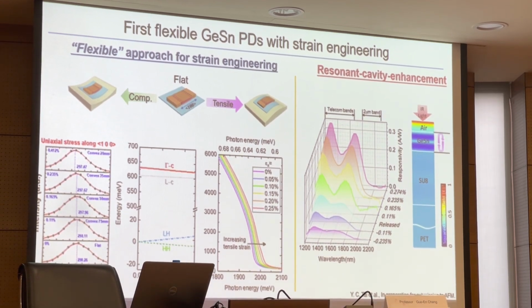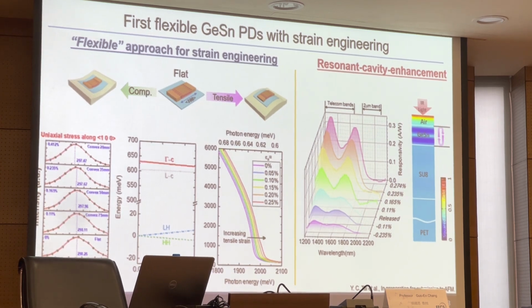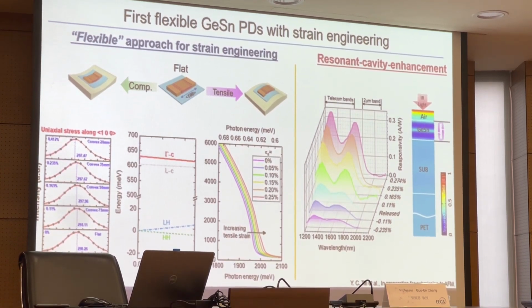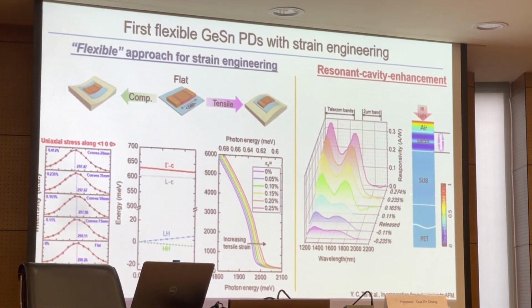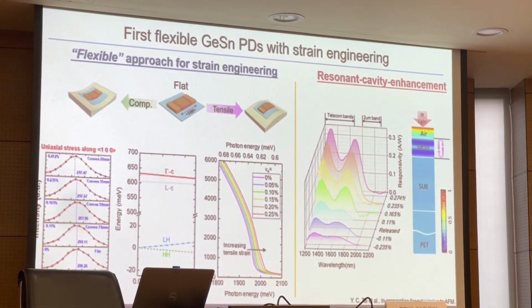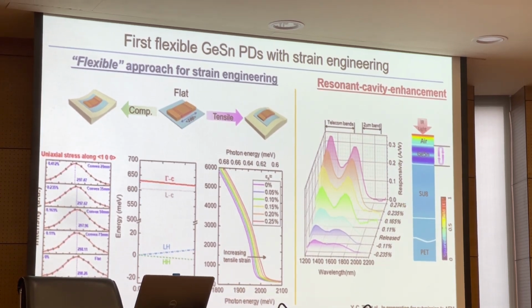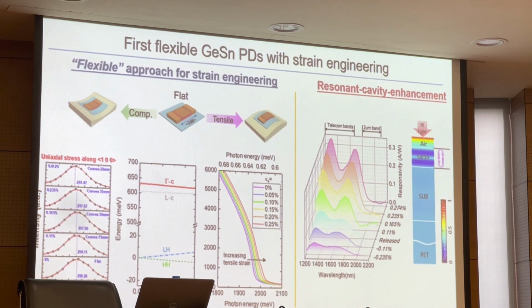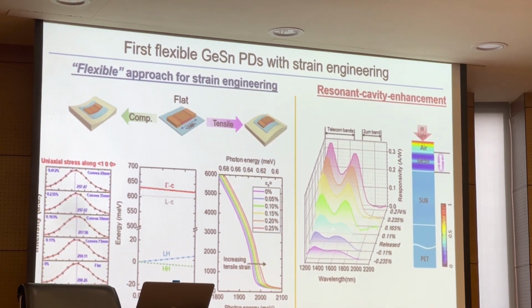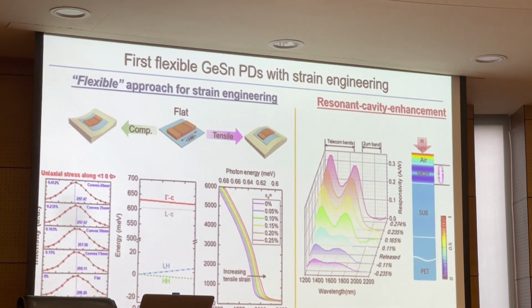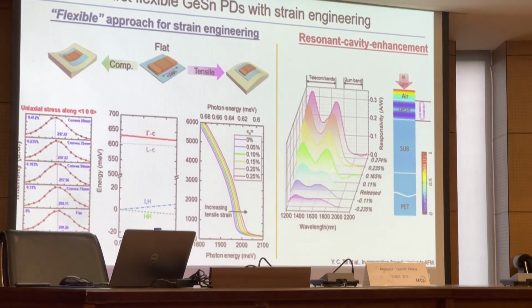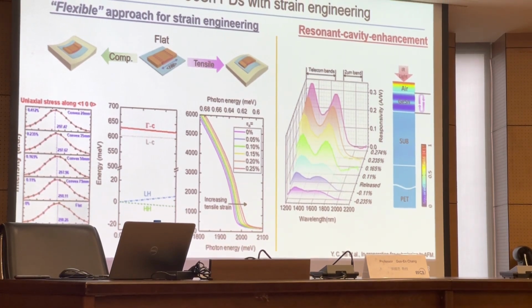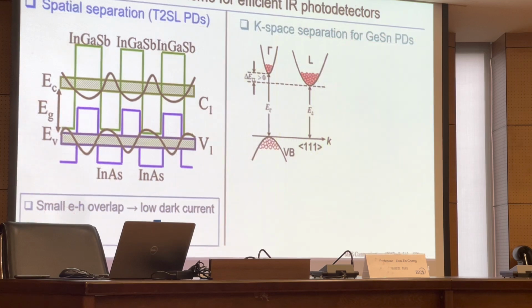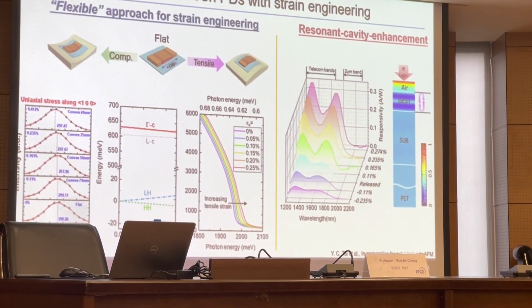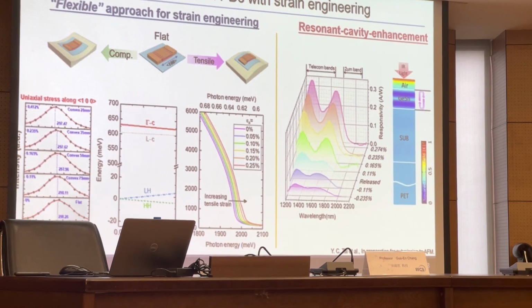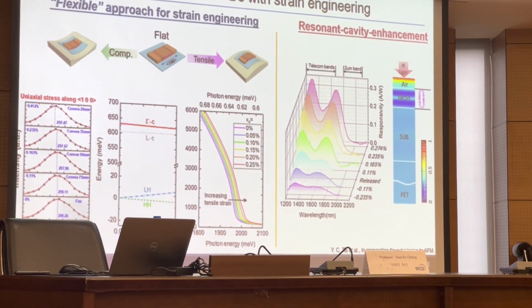This figure shows the experimental measurement of responsivity for devices with different bending radii or strains. Using this technique, we can introduce 0.274% tensile strain into our device. Compared to the device without any bending, introducing tensile strain allows us to amplify the responsivity by a factor of 3. This is a very remarkable value—just by bending the device, we can enhance the sensitivity by a factor of 3.